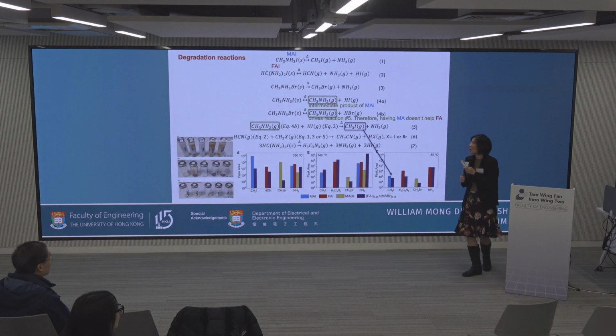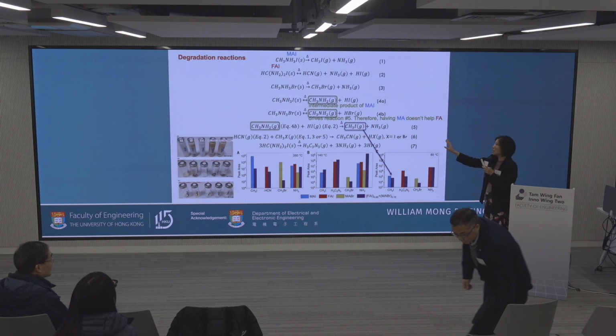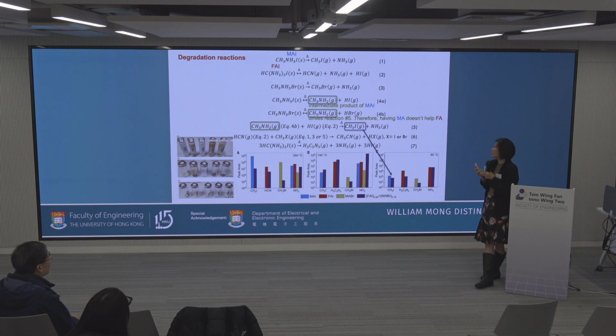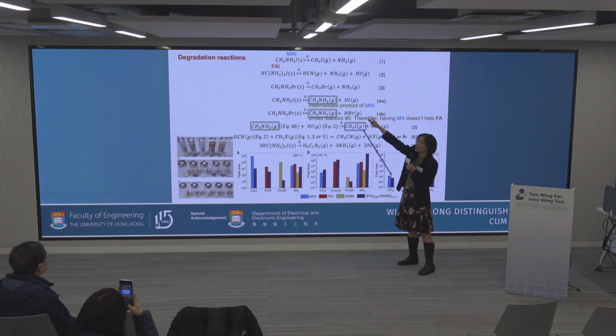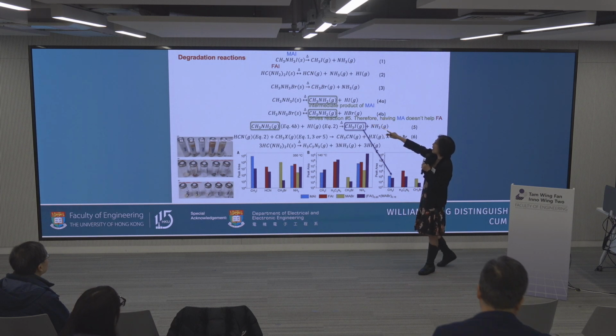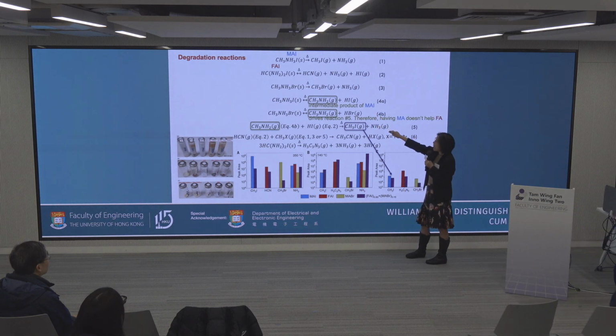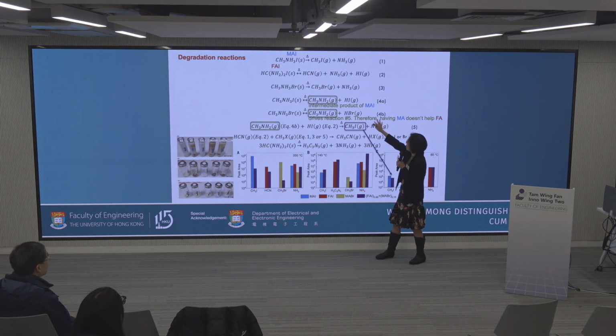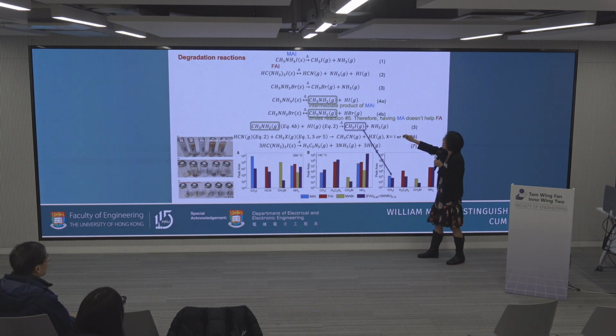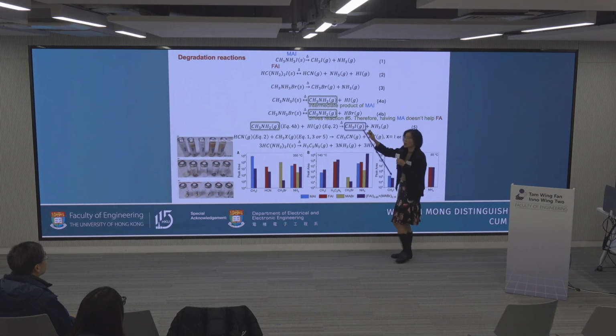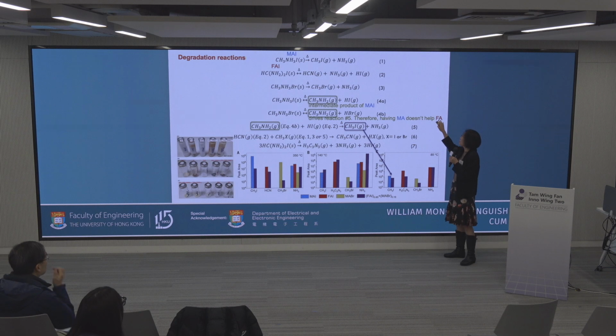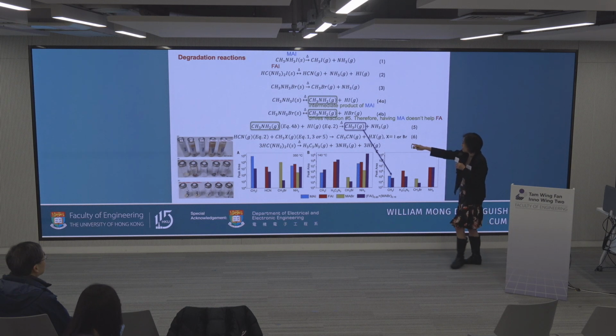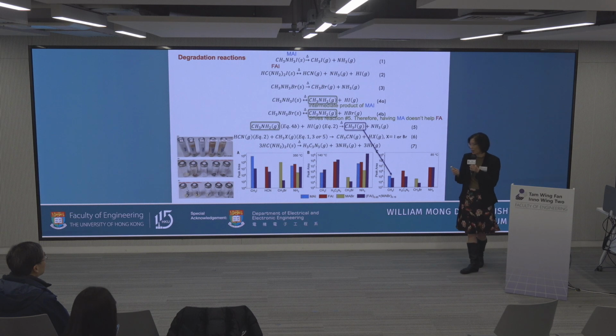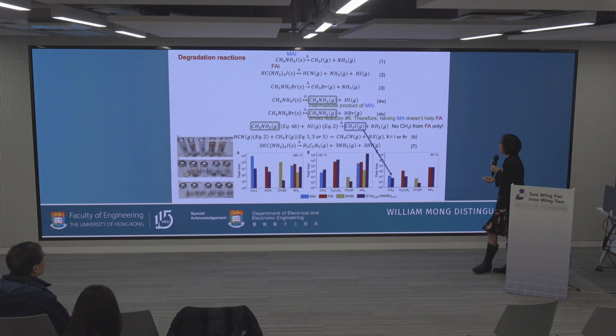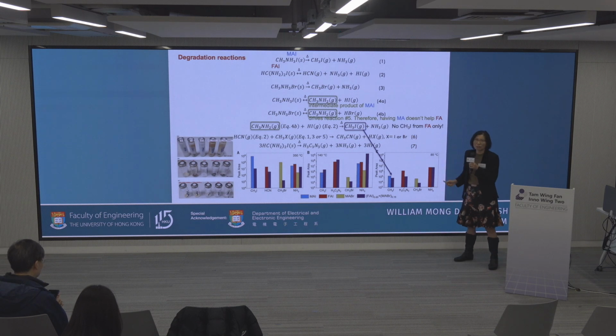So from the precursors, we used the outgassing products to write a whole bunch of decomposition reactions. You can see that CH3I is the main outgassing product from MAI, and then you have the HCN and NH3 from the FAI. We also get the intermediate products of MAI, and these are not good because they actually further drive the decomposition reaction in equation 5. These come out if you have the methylammonium. So having MA in, even when you mix it with FA, is not good because it drives the next decomposition reaction. So you can see that you will get the CH3I out of that when you have the mixed MA, FA perovskites. If you just have FA alone, you won't get that CH3I outgassing.